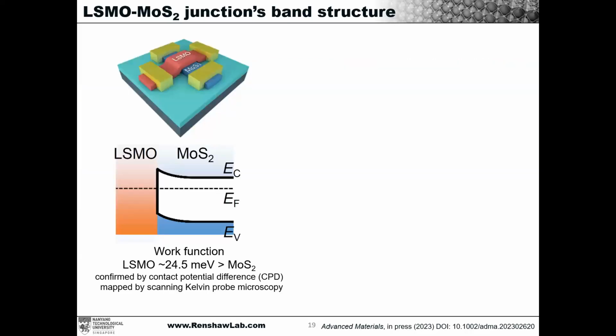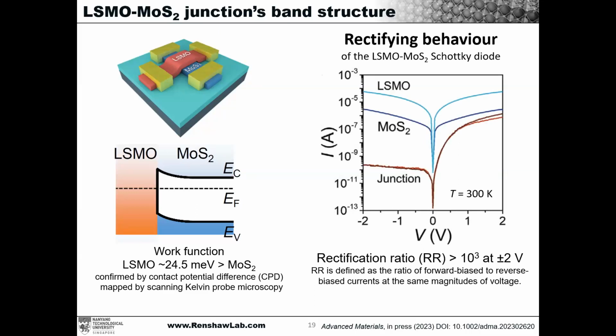So what kind of alignment do we get here? The work function of LSMO is typically about 20 plus meV above MoS2, and this is confirmed by the contact potential difference, of course mapped by the AFM. And then because of this band alignment or the band bending, we can observe the rectifying behavior at the interface between LSMO and the MoS2. The rectifying ratio is on the order of 10^3, or 1,000 times, if we apply positive and negative 2 volts. Of course, this is unique to the heterostructure or the heterojunction, because if you measure purely LSMO and MoS2, there's no rectifying behavior. And that makes sense, right?